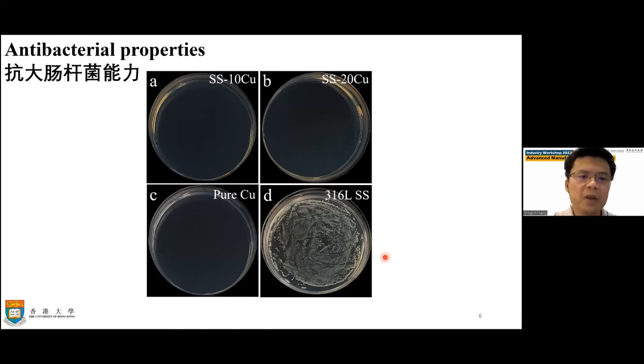And in addition to the antivirus properties, we also check our antibacterial properties. So clearly, pure copper is also very good. You don't see any bacteria here, okay? So this is the stainless steel. After 24 hours, you see a lot of bacteria. So normal stainless steel doesn't have this antibacterial property, and also does not have the antivirus properties. But pure copper has the antivirus property, and you also have antibacterial properties.